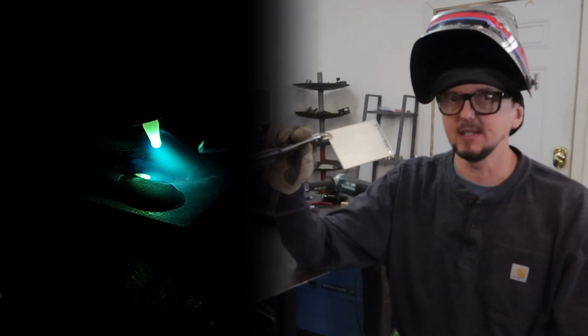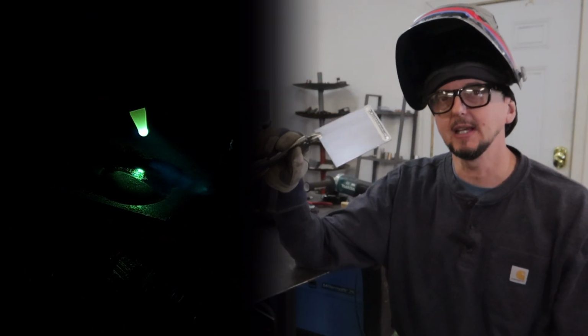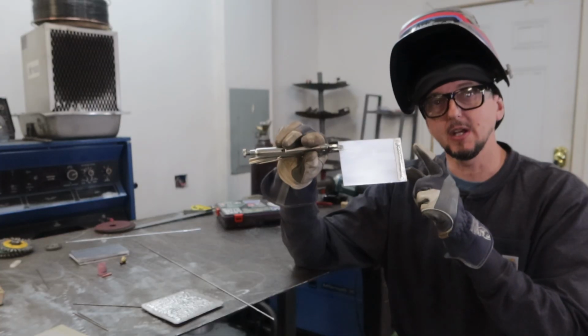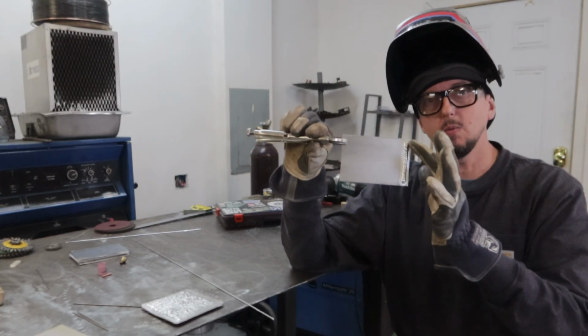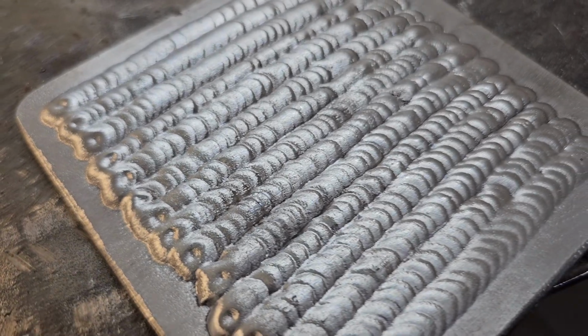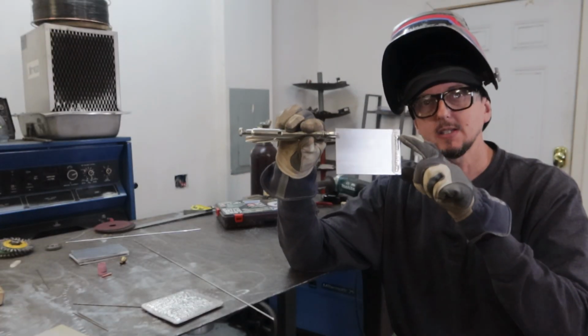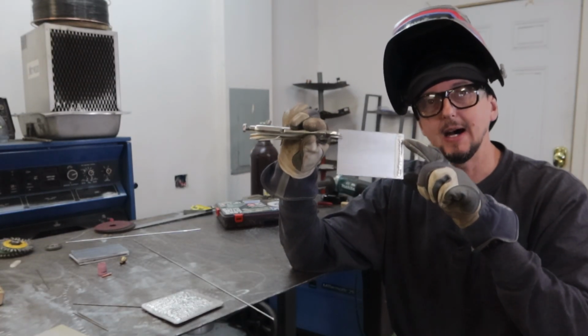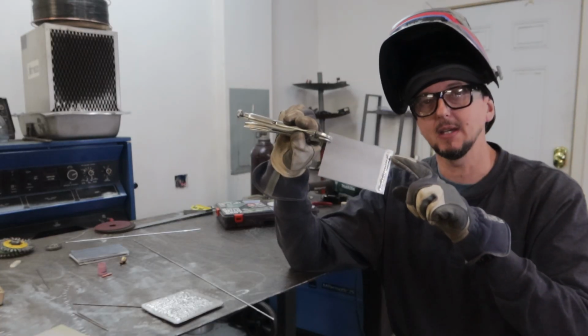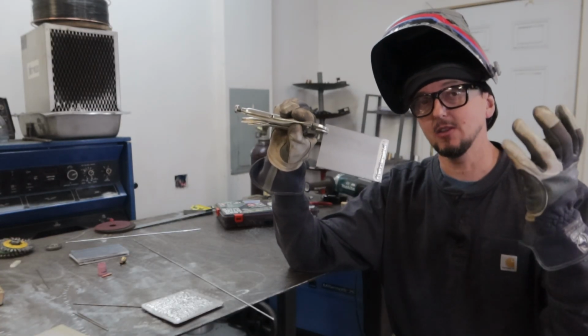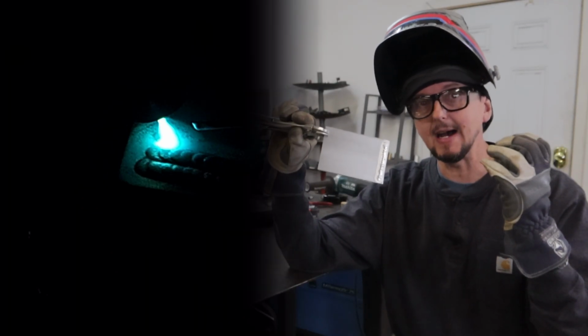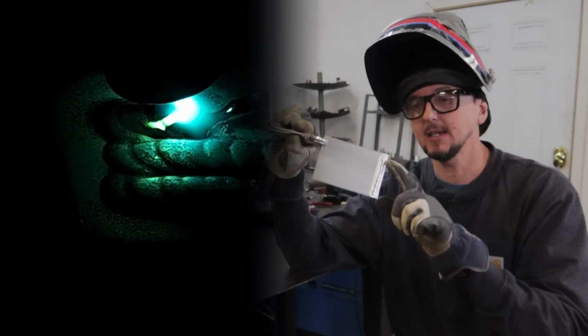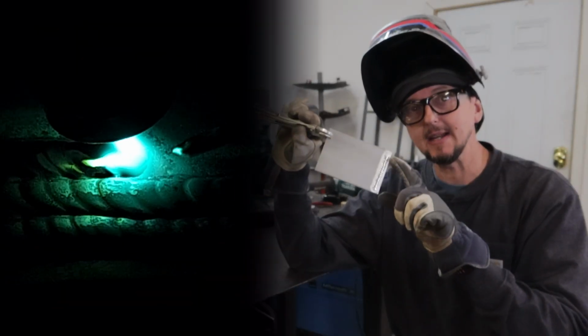Now, the other thing that's very, very important with aluminum welding, and we see this a lot in aluminum welding, is to reduce the crater. So we don't want there to be a crater at the end of our weld. That's the hottest portion of our weld. We're going to get a lot of shrinkage, especially in aluminum, because we have that high thermal change in size from heat, which causes that higher rate of distortion that we're talking about. So we have to add a little bit more filler metal at the very end of our bead.